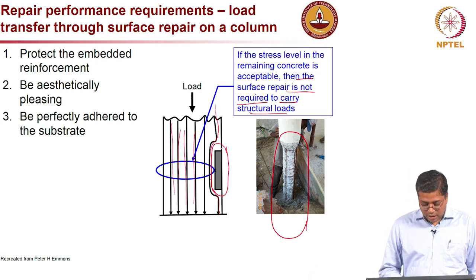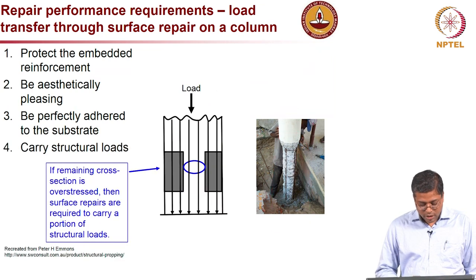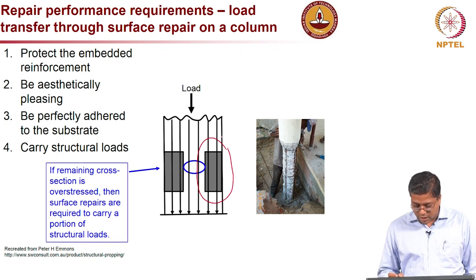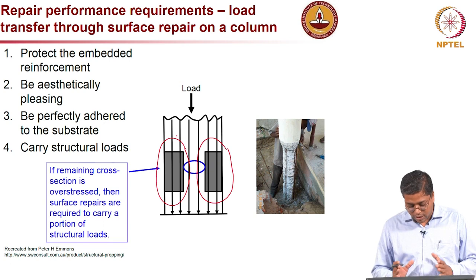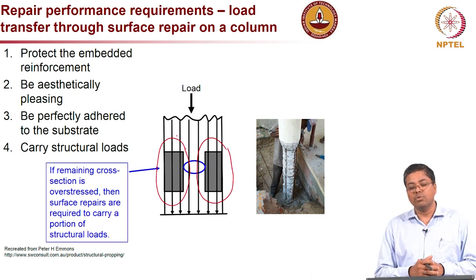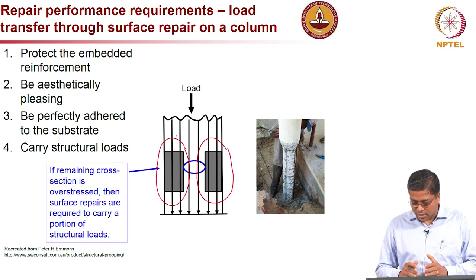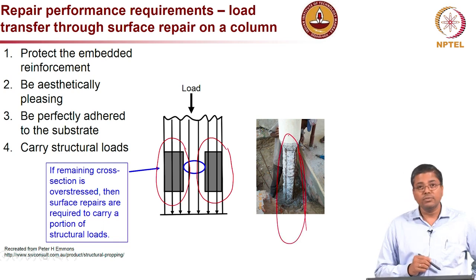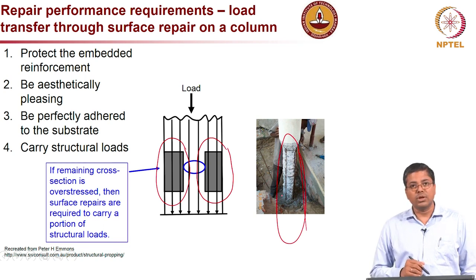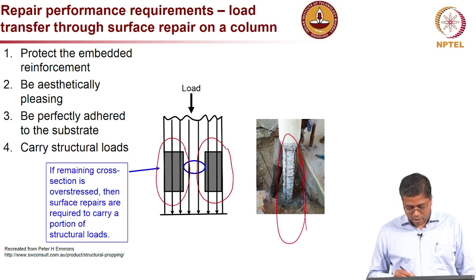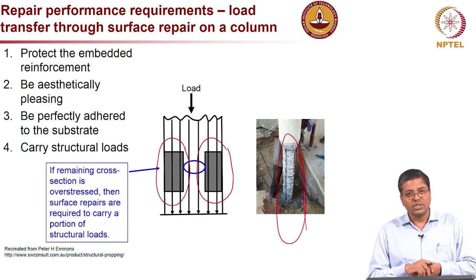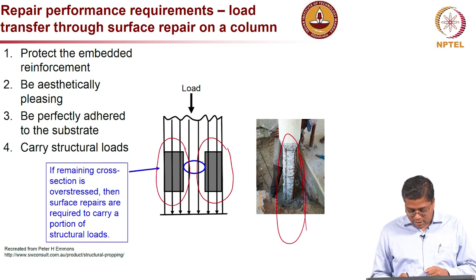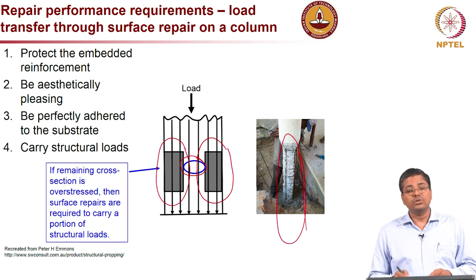Okay, but if the amount of concrete repair material is more, like in this case you can see here, then there is a deeper or larger amount of repair material. In other words, there is significant damage and more cover concrete is removed, and then you are replacing that with repair material. This is probably the case as you see in this picture here. You can see that the entire concrete cover is removed in this particular column, and then you are providing a whole new cover concrete. And in such a case, if the cover concrete is not taking the load, then the stress taken by this concrete, which is marked by the blue ellipse at the center, might be significantly high. So it becomes very important for the repair material to be able to take the load.